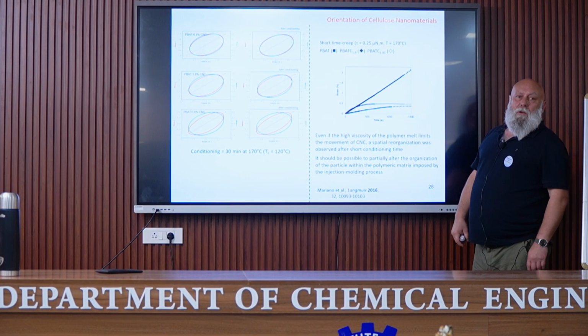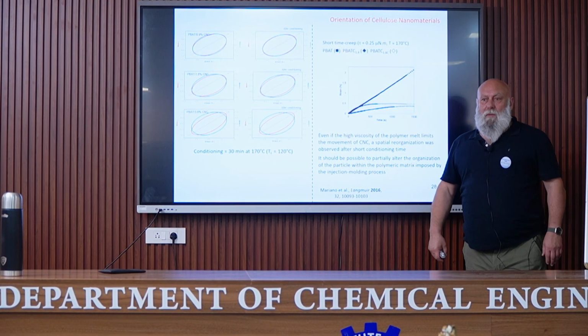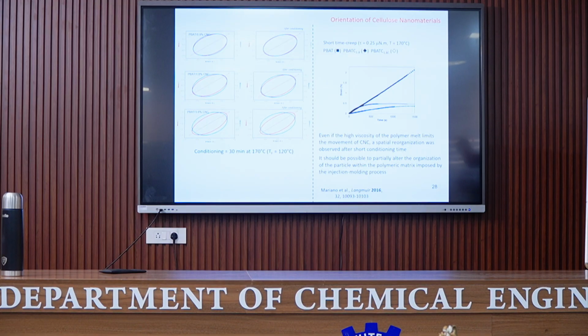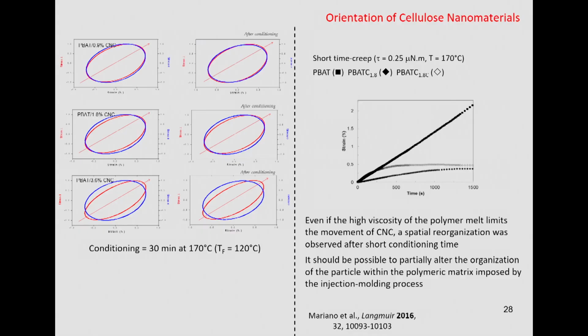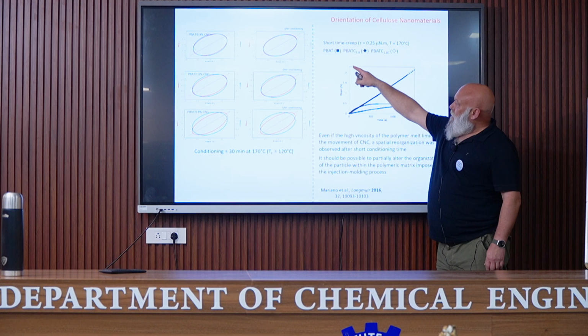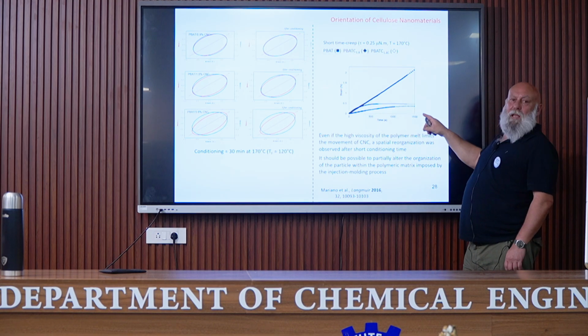This is a creep experiment. So creep experiment is a mechanical test in which constant stress is applied to the material. You can imagine that you attach a weight and you evaluate the variation of the elongation of the material, or the deformation of the material, as a function of time. So this was done here at high temperature, above the melting point of the polymer, for the pure matrix. So this is the strain as a function of time.